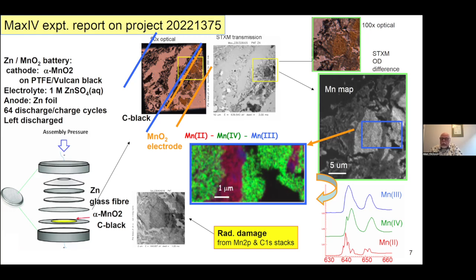So my group has done a lot of quantitative studies of that, and roughly of the order of 100-fold advantage in terms of the dose the sample will tolerate before you get similar amounts of radiation damage. And so this is what you see here. The dark line at the top is where the beam sits for a slightly longer time, because it's got to accelerate from 0 velocity. And in this system, the beam is scanned downwards repetitively, so the vertical scans of the sample. And this darker line is identifying the starting point of the imaging. It probably did not seriously affect the chemical analysis, but it is something you have to be aware of. And one of the things that is important is that because we use a rectilinear scanning, most STXMs do, you actually can identify modifications caused by radiation damage because they match the actual